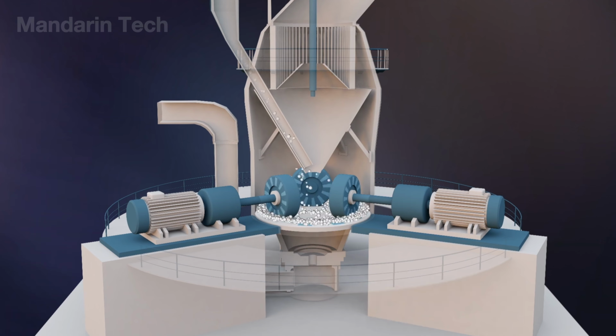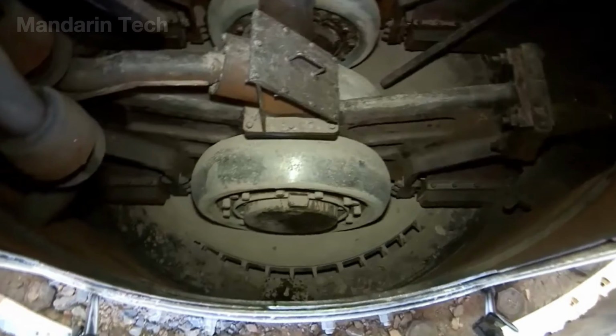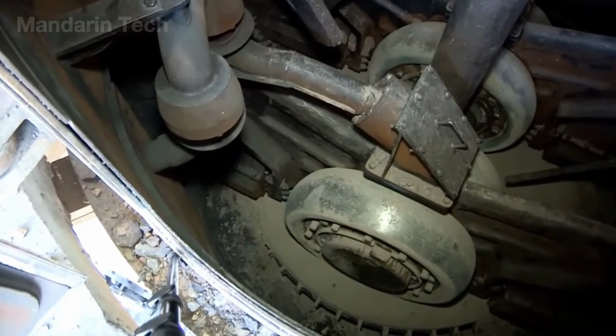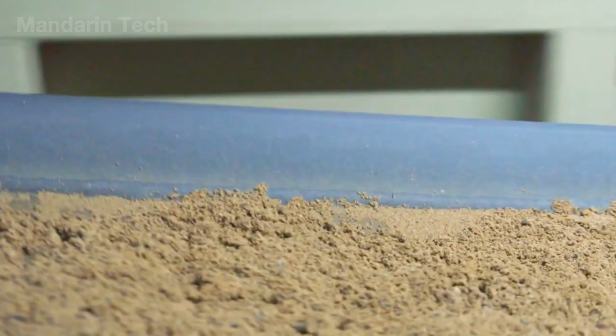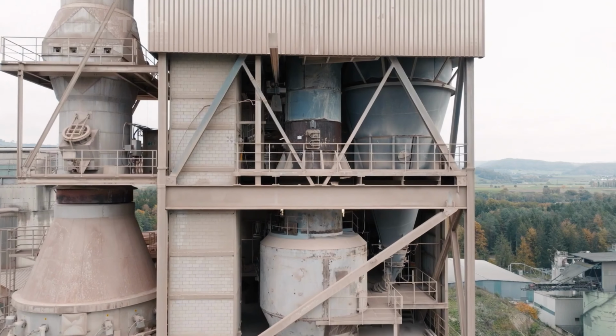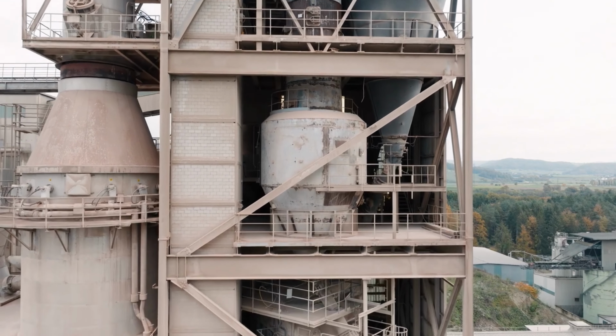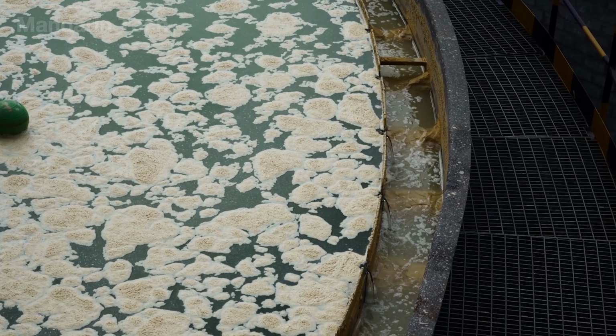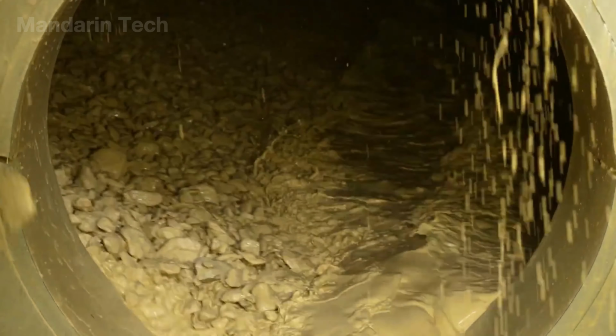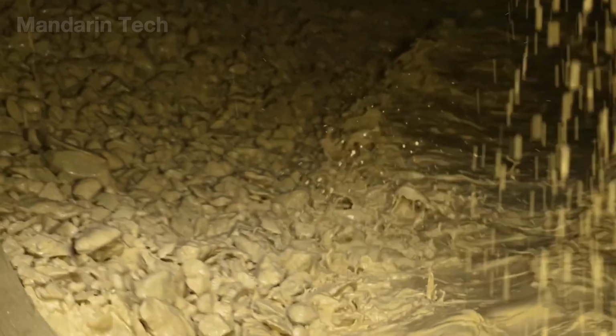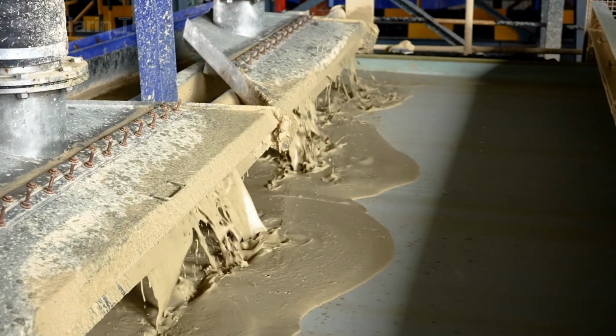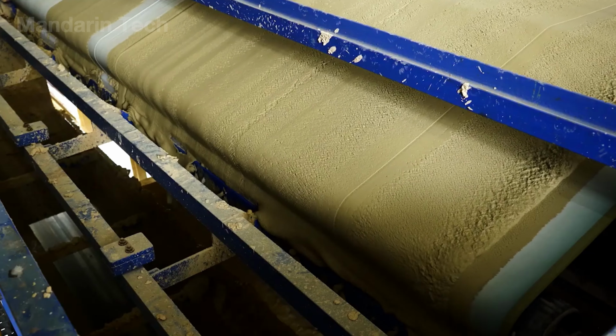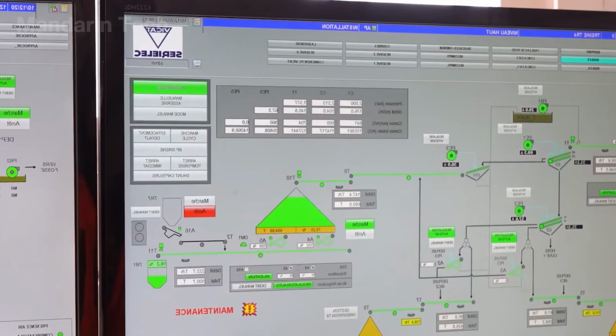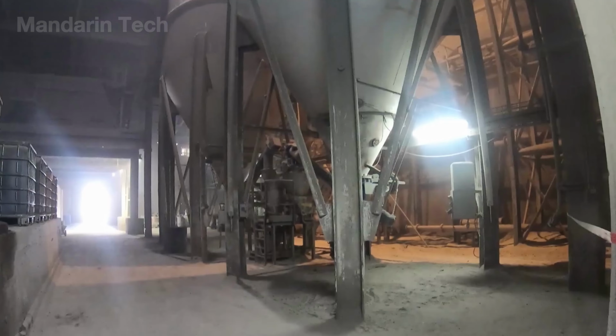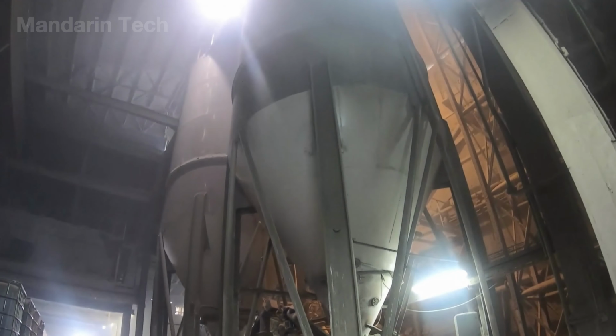Inside the grinding chamber, the intense compressive forces and friction from the rollers or steel balls break the material down to particles smaller than 90 microns, producing raw meal with a high level of uniformity. Some older production lines still use the wet grinding method, adding water to create a slurry. This approach makes chemical control easier, but consumes significantly more energy, so it is gradually being phased out in favor of more efficient dry grinding systems. Throughout the entire process, all operating parameters, including feed ratios, grinding speed, fineness, and gas temperature, are monitored in real time by the SCADA system to ensure the raw meal remains stable and consistent before moving on to the next stage.